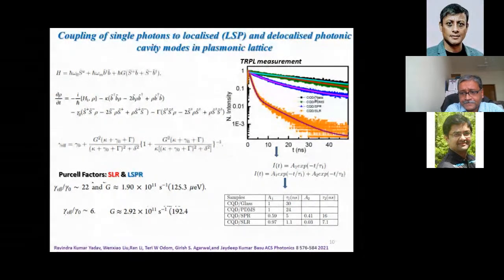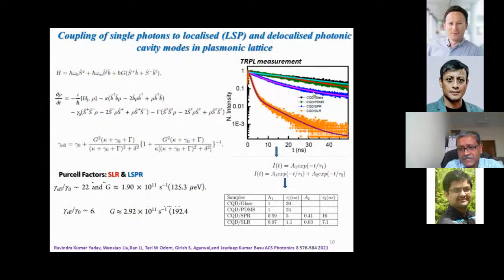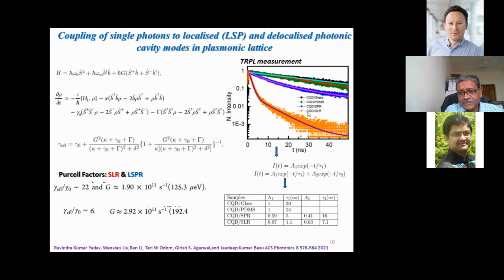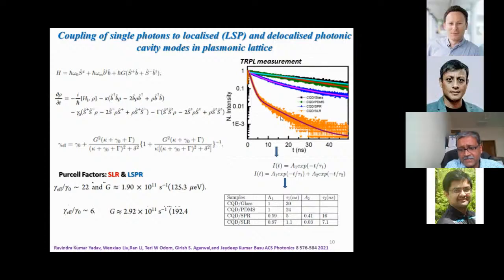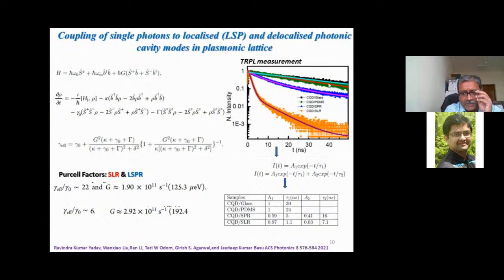When you now look at this blue curve, and I'll come to this, you start seeing that there is a deviation. There is a change because of the coupling to the LSPR mode. But then when you look at this system, you see a very strong change here, and you can see very clearly the existence of at least two distinct lifetime relaxations. This is the same quantum dots on, for example, glass, and then when it is on this template, you see that there is a very sharp change.